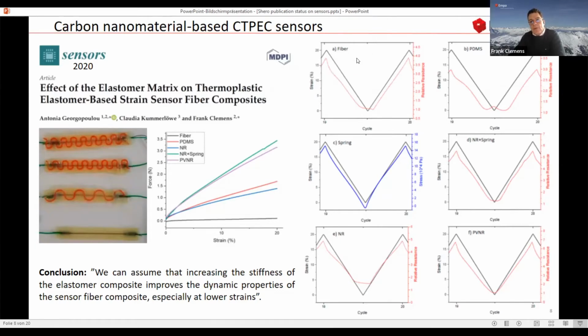You can see here the fiber, and if we use it now in a PDMS, which is typically used by the robotic people, you see that we get here a small increase in the sensing behavior. So that means we start here to get a secondary peak, as I showed you before, but not as strong as for this TPU material, which is commercially available. However, what we could see then, if we put a spring inside, which gives me clearly an elastic behavior, or if we work with natural rubber, we can completely neglect this secondary peak when we pre-vulcanize this natural rubber.